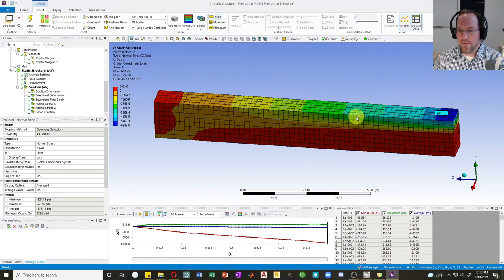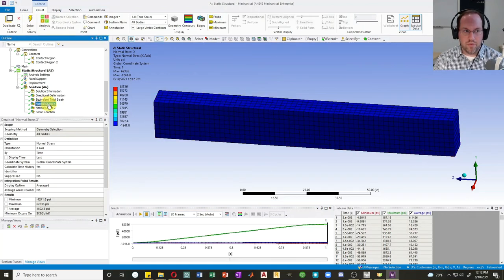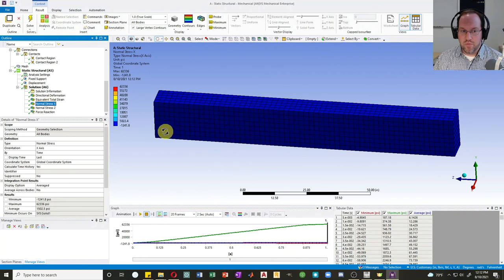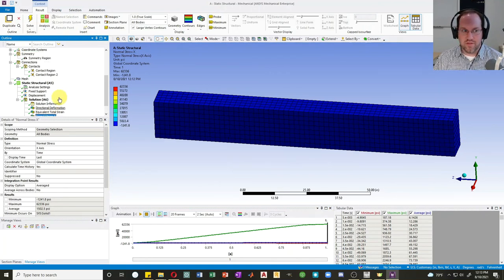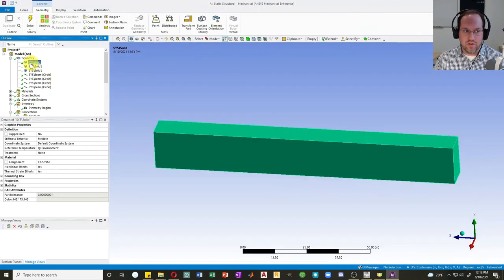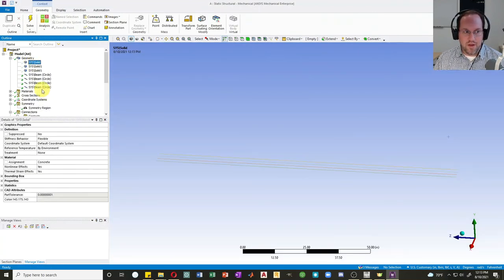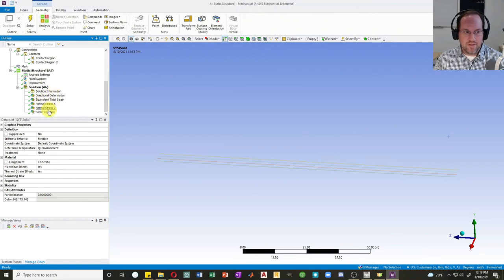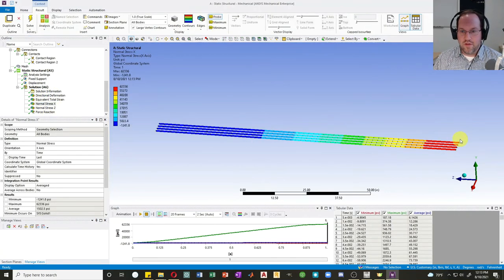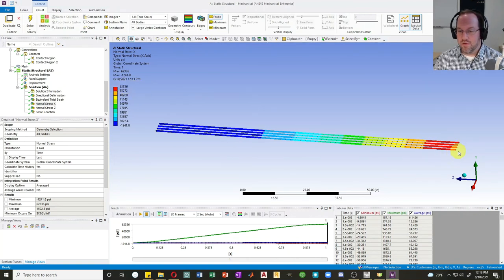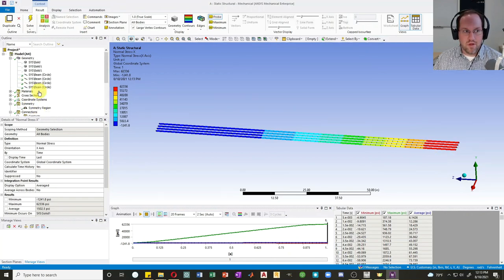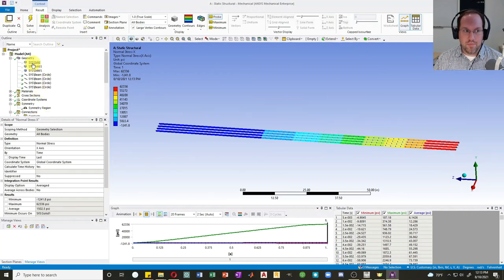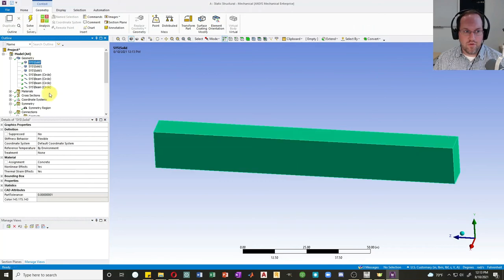We can also check out the rebar results. If I click normal stress x, x for the rebar will be your normal stress for that rebar. It's obviously invisible because it's hidden. So we'll once again hide our concrete, hide body, and go back down to our results for normal stress in the x direction. You can see that it's definitely yielding down here. It is above 60 ksi, so it's on the strain hardening plateau at my mid-span. Turn my concrete back on, show body.